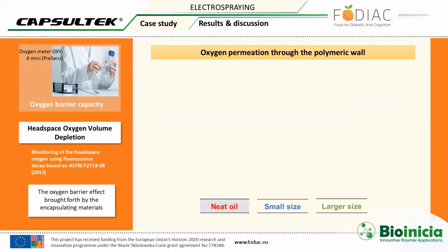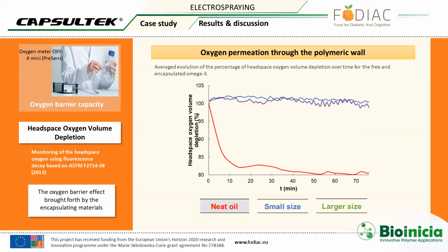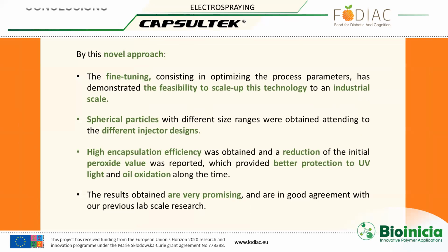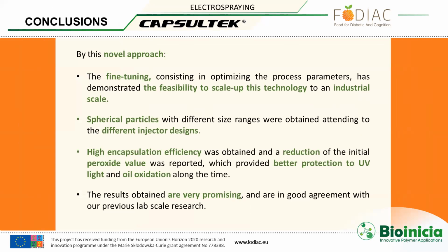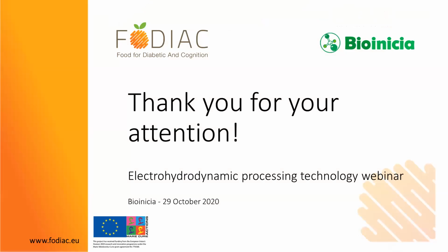And also, when we studied the permeation of oxygen through the polymeric wall, we observed that the oil consumed a lot of oxygen because it was oxidizing, whereas the particles remained completely stable. So with this process, we managed to increase the scale of the technology, maintaining the quality of the particles in terms of morphology, encapsulation efficiency, and stability to oxidation. And that's all. Thank you for your attention.